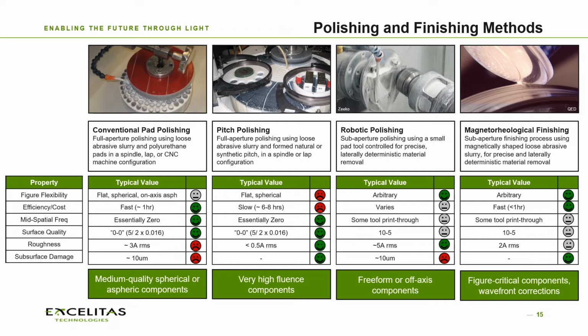and commonly are when there is a demand for a very challenging surface form that has to be held very precisely, maybe corrected for coating stresses and things like that. You typically won't achieve quite the surface quality, the surface roughness characteristics, in some cases the mid-spatial frequency or waviness quality that you will get with the more conventional processes like pad polishing or pitch polishing. But in some cases, that's really the only option. If we're talking about larger optics that have non-spherical form, we're typically going to be going to one of those other processes.